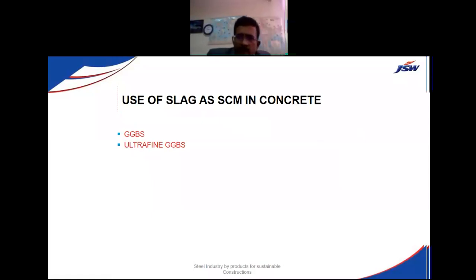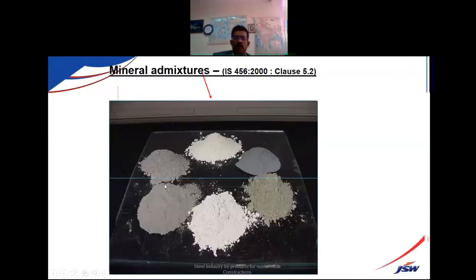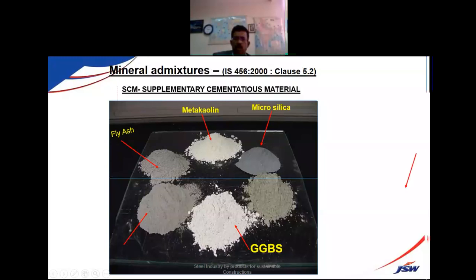So coming to the next stage of the product, the slag can get converted into GGBS, ultrafine slag, and cement. So we take that blast furnace slag to the cement mill using a vertical shaft mill. We grind it to a fine powder. So this becomes part of a cementitious material. It's called GGBS, a very eco-friendly product, and close to 3 million tons per year is being consumed in South and Western India.